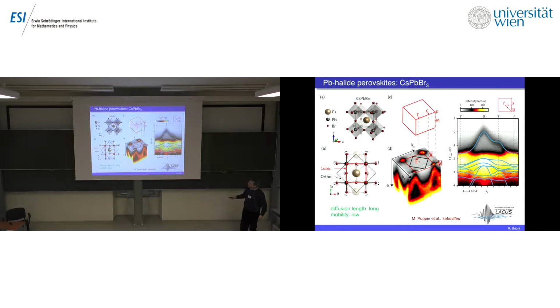Okay, more recent results, we have looked at lead halide perovskite, cesium lead bromine. As you know, these materials are becoming fairly interesting for solar energy conversion and other applications. Now, in this kind of system, the carriers have a long diffusion length, which is interesting if you want to use them for solar energy conversion. But at the same time, there is indication that the mobility is low. So the low mobility is an indication that polarons perhaps may form. So we looked at this material with ARPES.